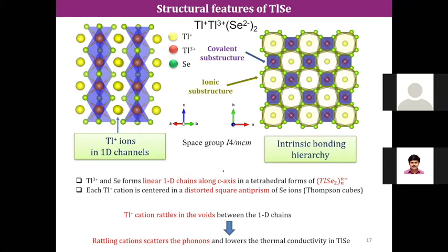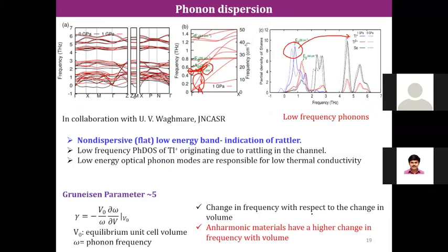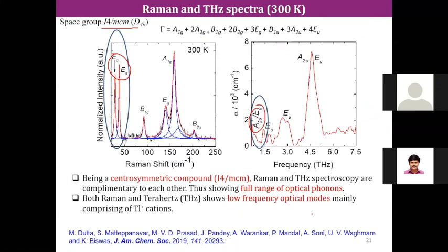Someone has to create this intrinsic bonding hierarchy, a strong bonding framework and a weak bonding framework. The strong bonding framework takes care of the charge transport, whereas the weak bonding framework takes care of the phonon transport. So we are decoupling the electronic and phonon parts into different bonding or different sublattices in a material, which gives rise to ultra low thermal conductivity. Okay, so this is the first example I have given of intrinsically low thermal conductivity without doing nano, meso, or microstructuring or point defects.